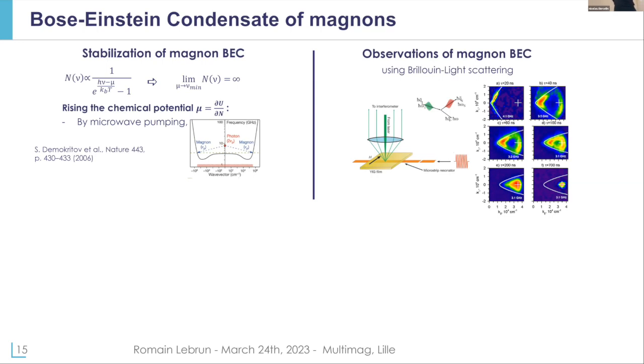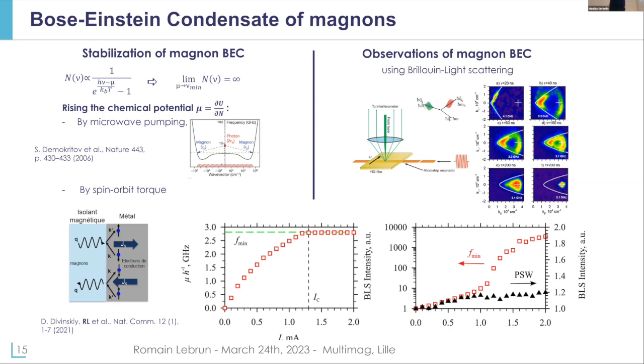What we have been trying to do in recent years was to show that this is also doable using spin-orbit torque, where we use electrical current to generate magnons. As Matthias said, if you put current in a heavy metal you can generate some bias at the interface that will increase the magnon population, and if you reach a threshold level you will see that the chemical potential is stable and the population of magnons at the bottom of your spectrum is increasing drastically, corresponding to a Bose-Einstein condensate. This highlights the quantum behavior of magnons in nanostructures.